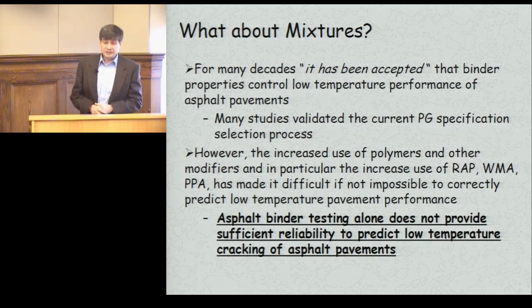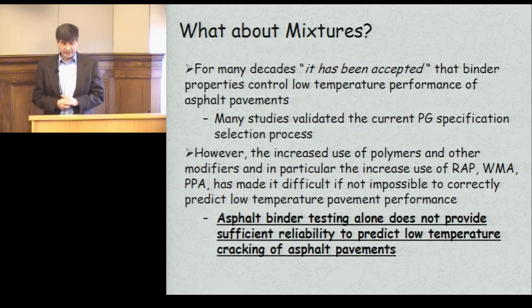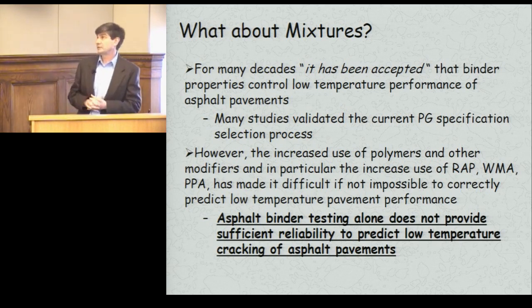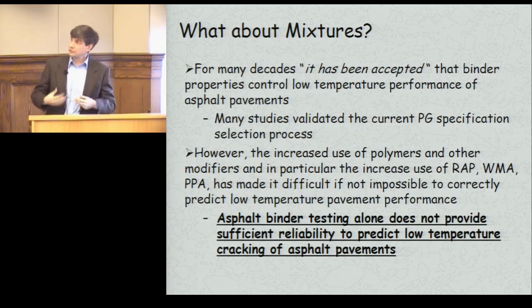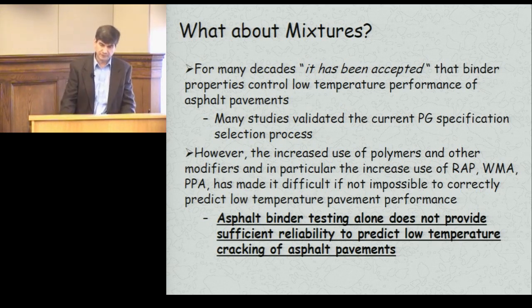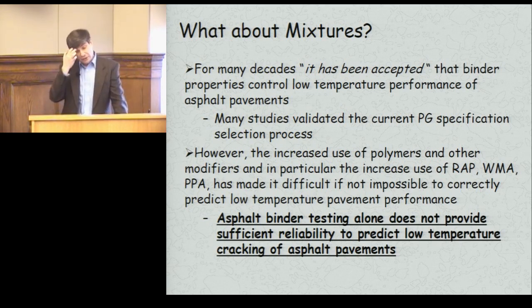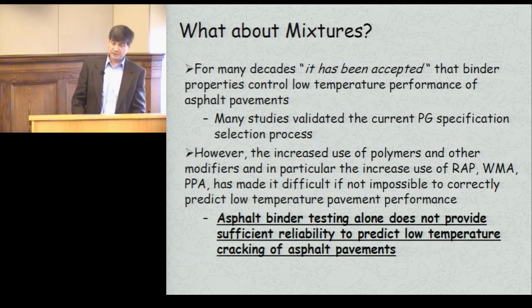I mean, ultimately this is what we put down in our asphalt pavements, and it would be nice to have an idea of the quality. Of course we do, but a better idea of the quality of these materials. So due to the addition of these new materials and the use of new technologies, asphalt binder testing alone does not provide sufficient reliability to predict low temperature cracking of asphalt mixtures.